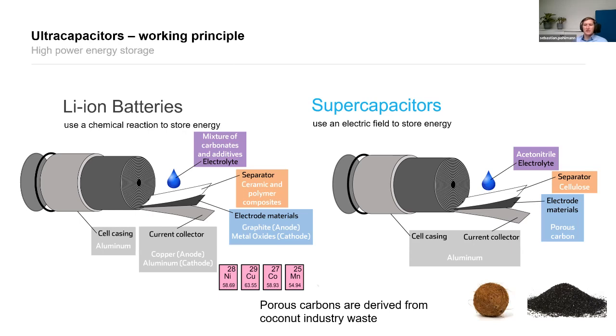Then supercapacitors are fairly simple. You have aluminum foil on both sides coated with a porous carbon. Most of the time, this is activated carbon made from coconut shells. And you have a paper separator that separates the 2 electrodes, and the electrolyte is most of the time, in 95% of the cases, acetonitrile based. And that's about it for the industrial supercapacitors that you can buy today on the market.